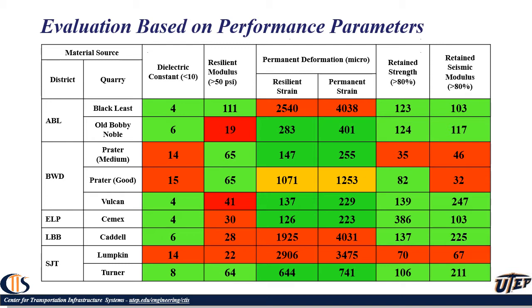Now, instead of the gradation and the plasticity, we started looking at the dielectric constant as an indication of the moisture susceptibility, resilient modulus to get the modulus of the material, permanent deformation, and retained strength. That will be the strength before moisture conditioning and after moisture conditioning, and retained modulus the same way. And the limits are shown over there in the graph.